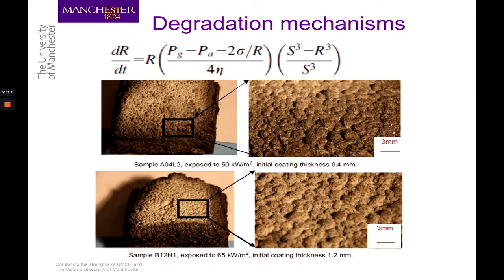viscous liquid may become too viscous, which then inhibits expansion, or too liquidy, so that the expansion will simply burst, or there's too much blowing agent, which creates too much pressure, or not enough blowing agent, which is not enough to expand. These are captured by two values in the equation which I mentioned before in my main presentation, the viscosity as well as the pressure inside the system. And of course, the final char has to be quite compact, because otherwise there's going to be a lot of thermal radiation within the system. And when you expose it to the environment, all these things can change because the chemicals get lost in the environment.